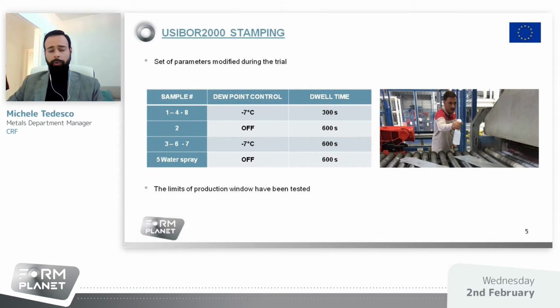The dwell time usually for the pre-hardening component with a thick layer of coating is between 300 and 600 seconds, while the dew point generally is set up around -7, -5 degrees centigrade. But we tried also to modify this parameter to see what could be the results on the final